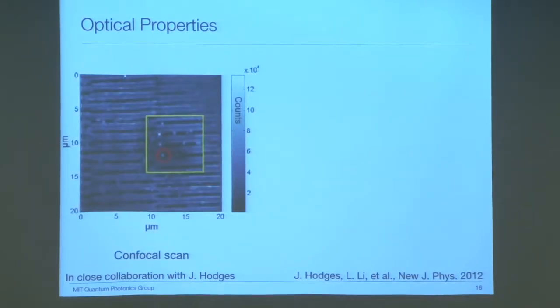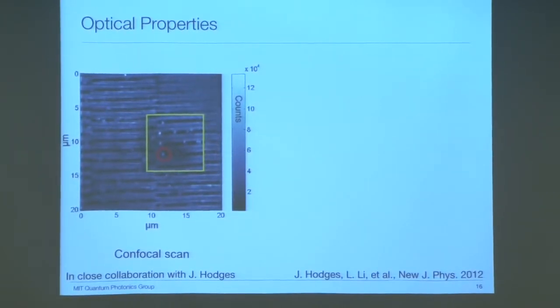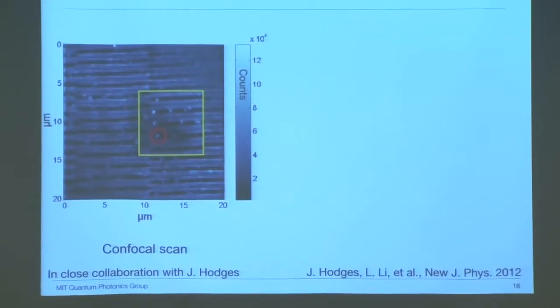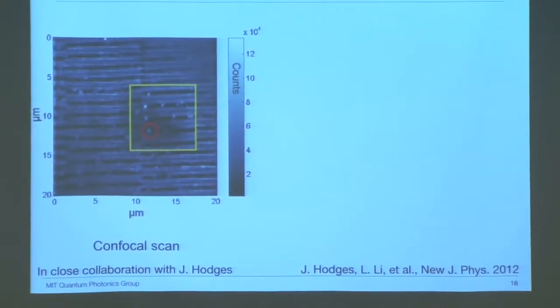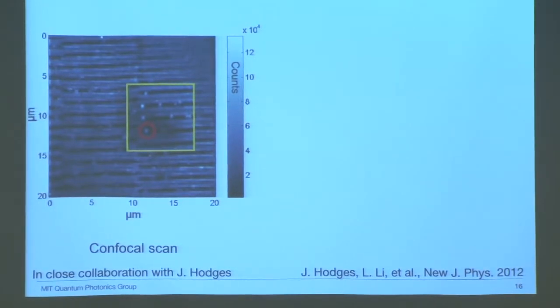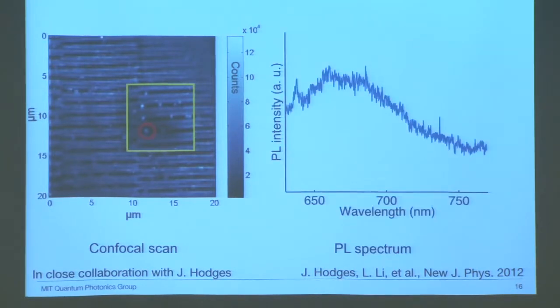Let's see how good their optical properties are compared to the previous method. The optical measurement is in close collaboration with another former postdoc, Jonathan. This is a confocal scan of a diamond nanoslab still attached on top of the bulk diamond. This bright spot is a single nitrogen vacancy NV center, which was confirmed by second-order autocorrelation measurement and also the spectrum. It has a characteristic zero phonon line and a broad phonon sideband from 650 to 800 nanometers.